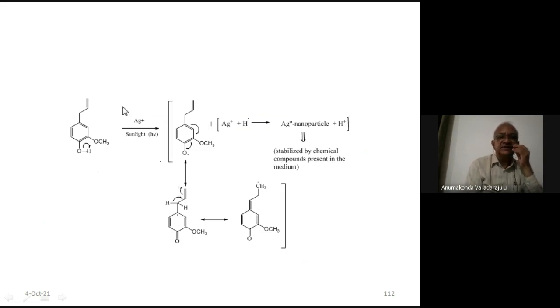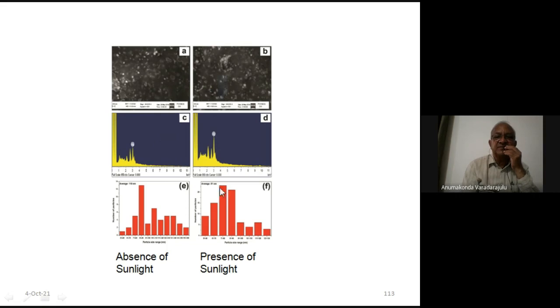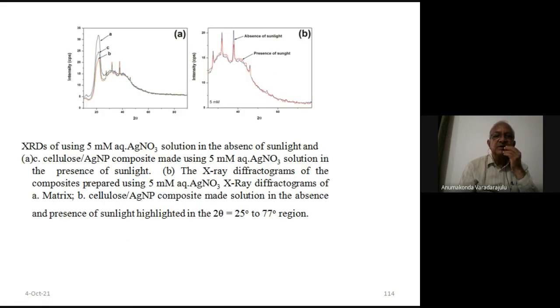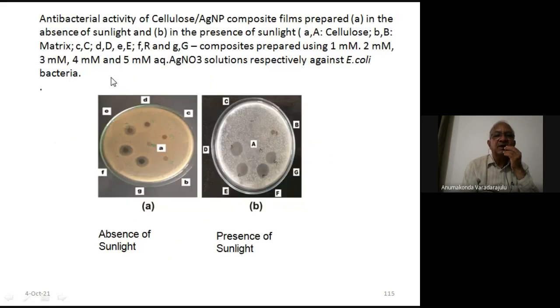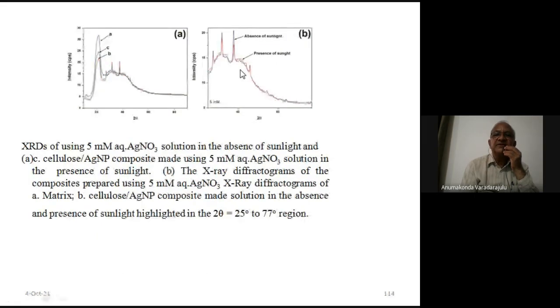What is a photochemical reaction? Sunlight acted as a catalyst and as an additional energizer, and it hastened the in situ generation process. So this is in the absence of sunlight, and this is the presence of sunlight. In the presence of sunlight, more nanoparticles were formed, with the increased intensity of silver, and the peak of the EDX spectrum has increased compared to the absence of sunlight. In presence, more particles are formed, and the distribution is somewhat narrower compared to the wide distribution in the absence of sunlight. So this is how we reduced the time. And these are the XRD spectra in the absence of sunlight and in the presence of sunlight.